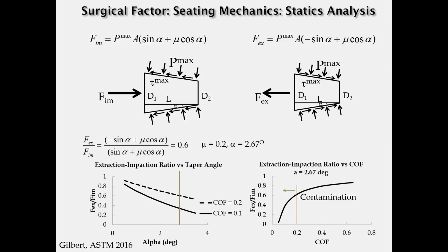But also, it's important to think about the mechanics of the modular taper junction, and this image here is a simple engineering mechanics analysis of the frictional interactions that go on during impaction of a head on a neck. And you can see that when you drive the taper into the head, the trunnion into the head, you develop a pressure and friction. And those frictional and pressure effects work against one another to lock that taper in place. When you try to extract the taper, then the friction switches to the opposite side, the pressure is acting to pull out, and it actually comes out at a lower force than the force you use to impact it. And in fact, that ratio of extraction to impaction force is roughly about 0.5 to 0.6 for typical conditions of a modular taper.